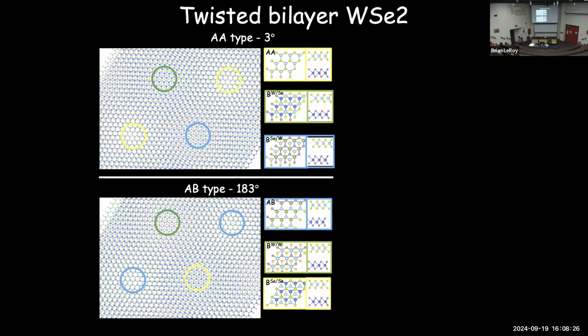And then if you start looking at how the chalcogen and the metal atom stack on top of each other, here there are ones where you have metal on chalcogen, chalcogen on metal. And in this one, you don't ever get that stacking. You get either metal on metal or chalcogen on chalcogen. And so there are actually 6 different high symmetry stacking configurations that you can have. 3 appear in this top case, 3 appear in this bottom case.